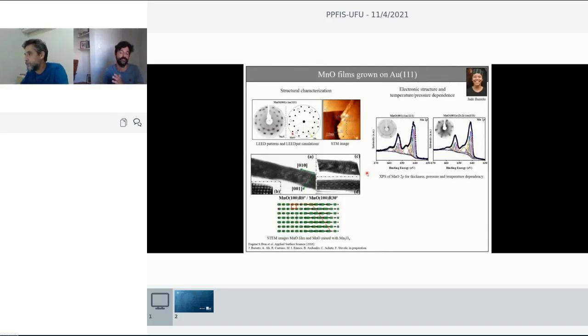Right, great. So then let's go for the manganese oxide itself. So here I have an example of what we have been doing. We have here manganese oxide, MnO, that's relatively inert, because the oxidation state of the manganese here is only +2. But we have grown these films on top of gold substrates. And this is some of the results that I can present to you.